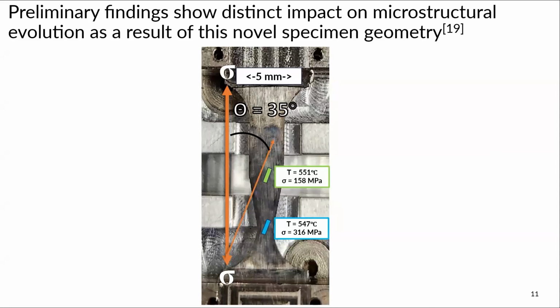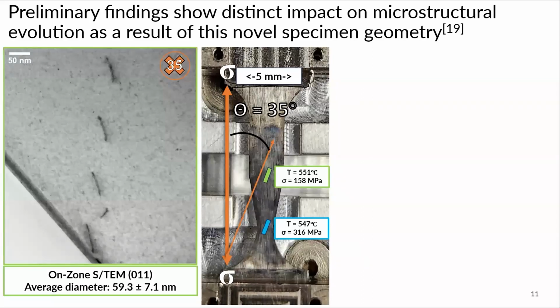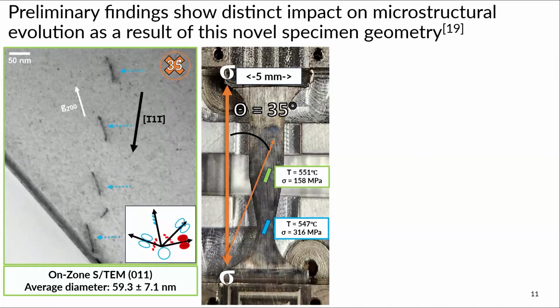And so for preliminary findings, the whole purpose of this was to see if we can generate multiple data sets from one experiment. And you can see we have very few dislocation loops that are traveling on the 111 plane. That's the primary slip plane in FCC material. And they're going towards a grain boundary, which is a sink. So dislocations and defects will go towards sinks.